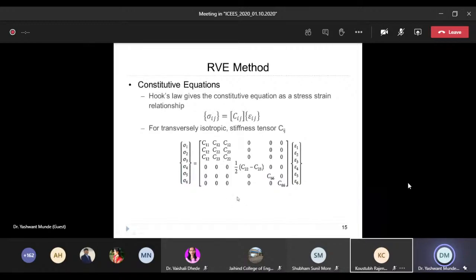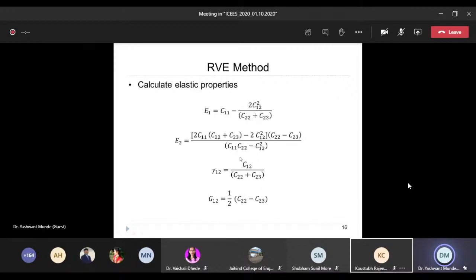So what is the way we can calculate the elastic properties? These are the equations for the elastic properties of the material in terms of the stiffness tensor coefficients. If you want to know the elastic modulus of the material in direction 1, we use the equation C11 minus twice C12 square divided by C22 plus C23. So these CIJ are the coefficients that we calculated here. How do we calculate them? Because the strain is unity, we know the stresses. So from the stresses, we can easily calculate CIJ.